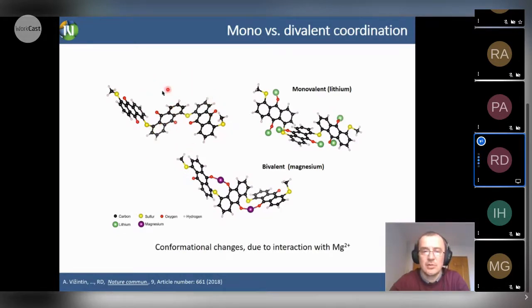So here we show how anthraquinone groups are connected through the sulfur linker into the polymer. And in lithium, we have a monovalent lithium which coordinates the quinonyl group. But once you have a divalent magnesium, then there should be some kind of difference in the coordination, and that is shown with this 5 inverse centimeter difference. That was also the first suggestion that we really have magnesium 2+ inside, and that we are using both electrons to coordinate 2 quinone groups, which are monovalent quinone groups. So here we need to be careful that the cathode is still monovalent.